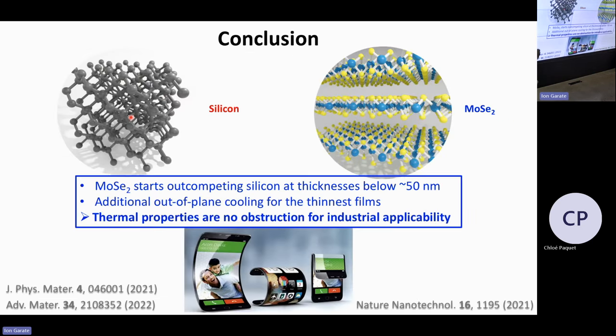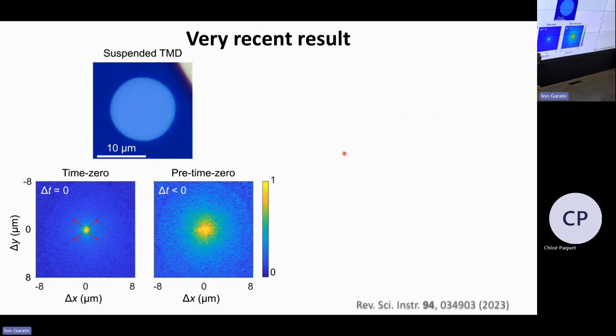So to conclude this part, what we see is that this TMD, and this is actually one of the worst thermally conducting ones, so there are ones that are much better, already starts outcompeting silicon in terms of thermal transport below a thickness of 50 nanometers. So we think that's quite interesting, for example, for applications of flexible electronics, because at some point you want materials that have good mobilities, but also good thermal conductivity. And then at some point you reach a thickness where silicon might not be your best choice. And we do end up with these TMDs that are already in some of the roadmaps to be incorporated for applications like this.